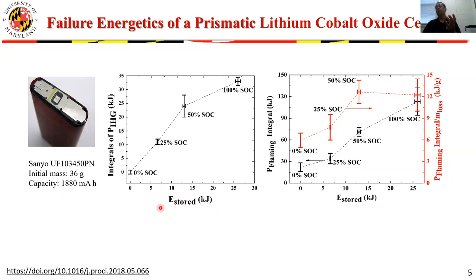That is not surprising. As I pointed out earlier, the chemistry that is responsible for generation of this heat during failure is not the same chemistry that is responsible for the charge-discharge cycle. But it increases linearly with electrical energy stored up to about 50% state of charge, which is also expected based on the chemical description of the failure that I provided before. And then it starts to flatten out after 50%. And that's what we observe for the majority of the cells. And the reason it flattens out is because this is the point of charge where you start ejecting a lot more materials from the cells before they have an opportunity to fully react.